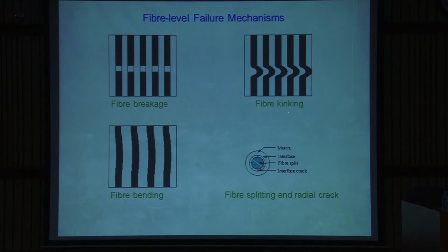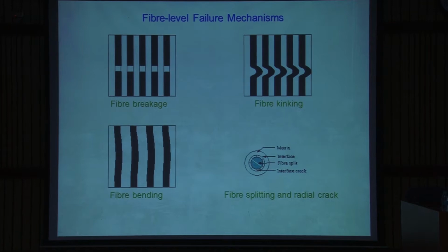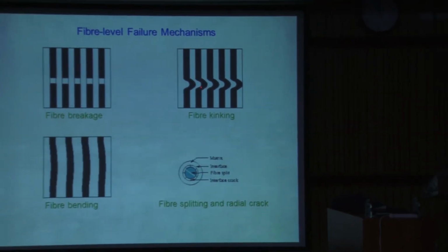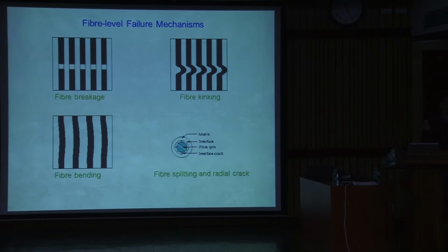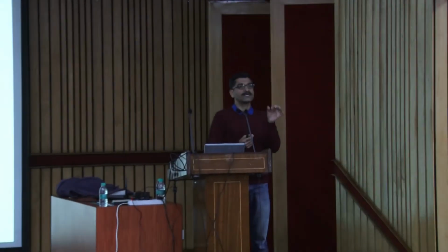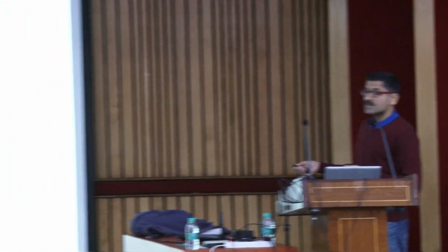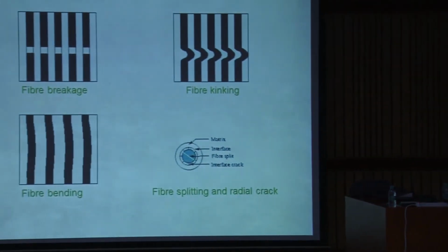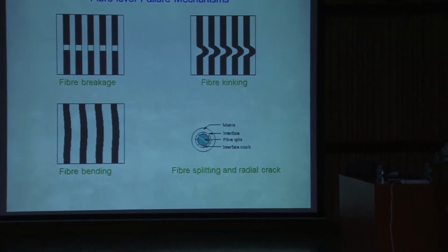Then another is fiber kinking. As I said, these fibers are very thin, just 8 microns or 20 microns, and they come in a bundle. You will have a bundle of 6,000 fibers, 12,000 fibers, 18,000 fibers or so. You cannot have individual fibers, so it comes in a bundle. Because of handling or some other reason, it is possible that it may have some kinks at some places. This is called fiber kinking.